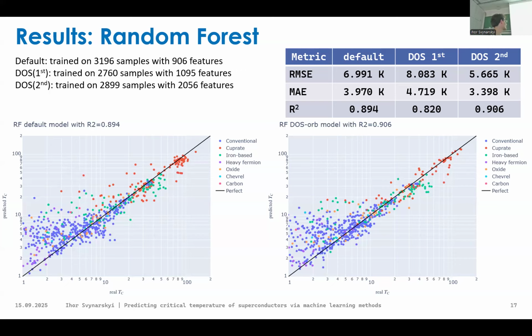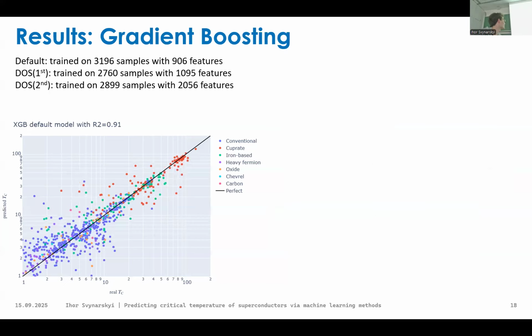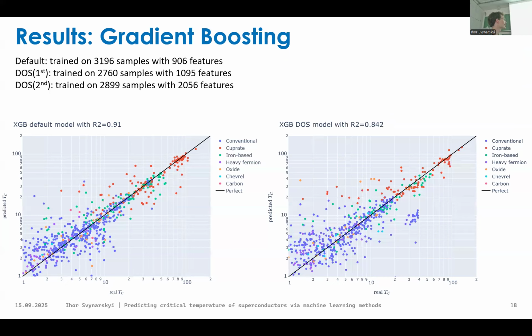And you can see that for random forest there is an interesting anomaly: it almost never predicts the Tc being lower than like 1.5 kelvins or something, even if we have materials with lower Tc. So in the region of low real critical temperatures, it overestimates the critical temperature, but it's only for random forest. For gradient boosting, there is no such problem. It's more or less predicting them on this line. But here you can see the magnesium diboride, this small region. It couldn't catch this.